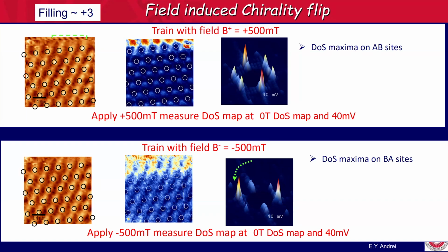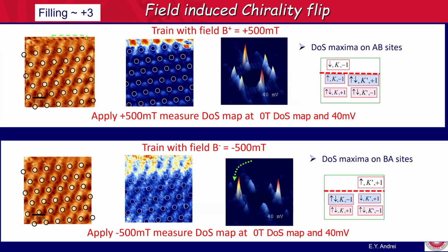Now unfortunately, this sample kind of crashed. So we have to make a new sample and look at QPI and look at the energy dependence. If this is an edge state response with a chiral edge state, we should see slopes of the QPI, of the energy as a function of momentum, that are in opposite direction when you train the sample, but we are not there yet. Okay, so this is the speculation. Maybe these are the states that are responsible for the observed quantum anomalous Hall effect.